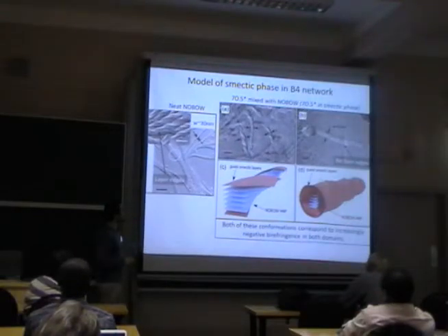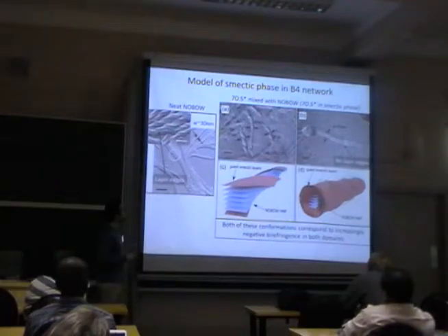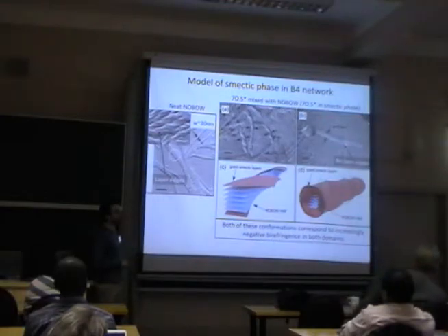And actually, we found something else too, a little less rare, but very, very thick helical nanofilaments with no visible layer edges. In this case, we believe that the same thing is happening as in this figure C here, but actually the guest layers are beginning to wrap around the exposed layer edges of the helical nanofilaments. So you can see here, as the layers grow and pile up, they actually grow over the layer edges until you get something that's shaped sort of like a cigar with this remnant helical ripple on the outside. So we can see that here.